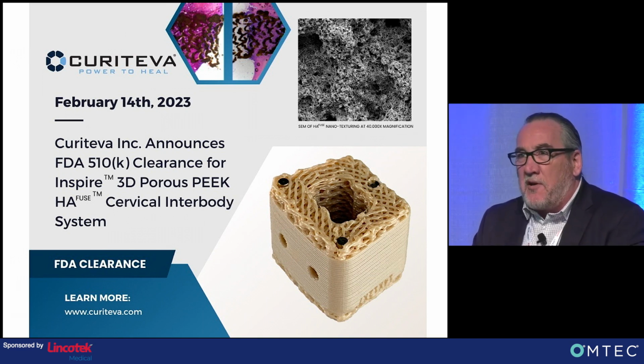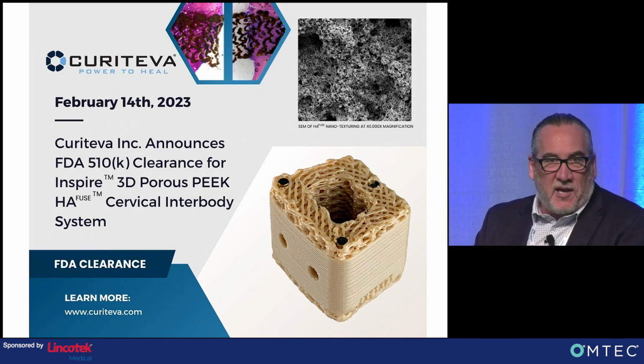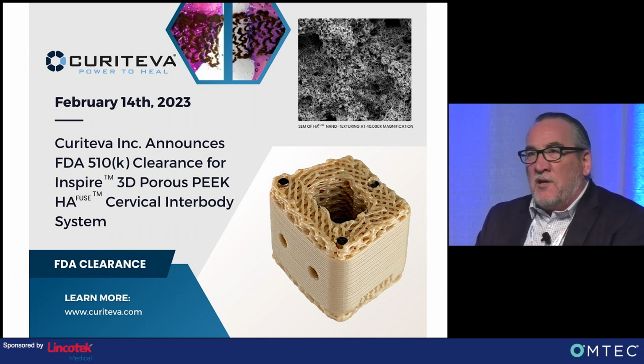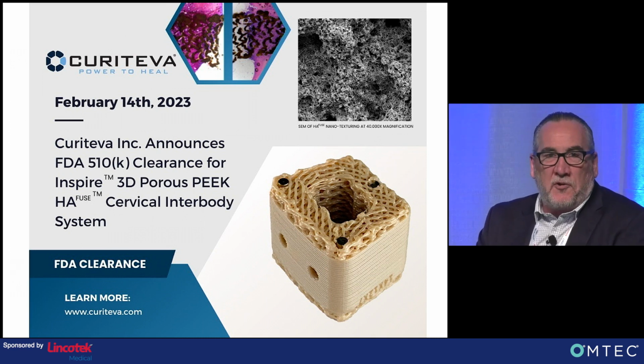There is some experience with titanium, selective laser sintering, where you see some of those fused linkages are very tough to control. And so unfortunately, when there is a failure, it can be catastrophic. You end up with a lot of particulate all over the place. We did not see any of that here. The toughness and the strength of each of these linkages is quite robust.